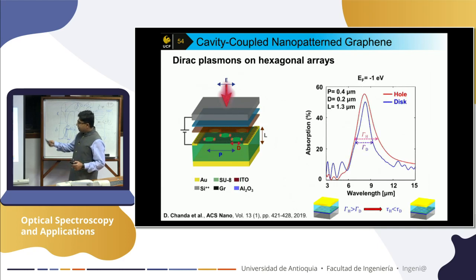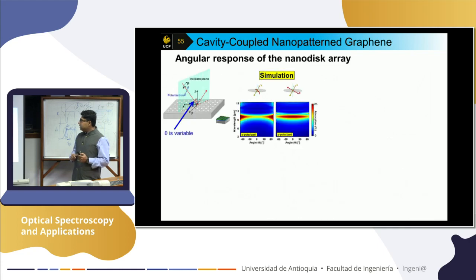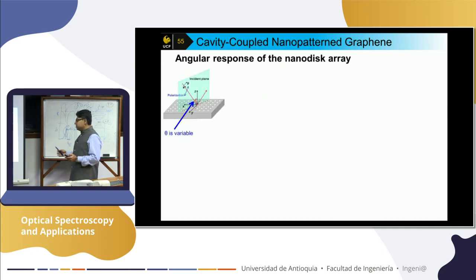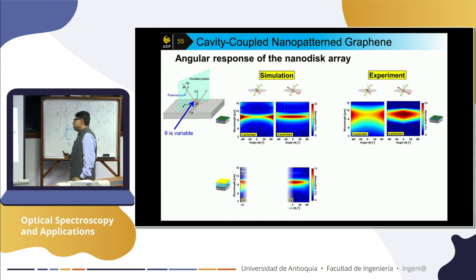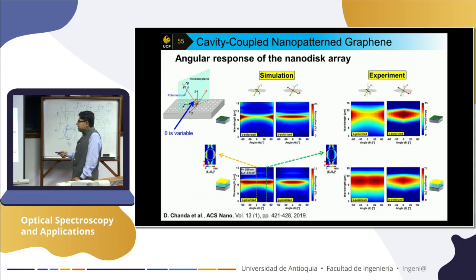Eventually you could go to about 60% absorption, which we promised. Again, the key goal was to see how angle sensitive it is, because you create the pattern on graphene. That showed this is quite angle insensitive, shown in simulation through finite difference time domain, FDTD, and experimentally measured. It means it doesn't matter what angle light comes from. We did up to plus minus 60 degrees, which is quite a broad angle, and saw a quite flat response. Your absorber can see a very wide angle.